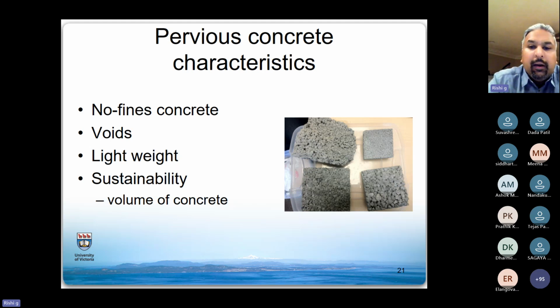Porous concrete or pervious concrete, of course, has lots of voids. If you look in literature, pervious concrete can have anything from maybe 5% of air voids all the way to 40%, 50% of air voids. The systems that you're looking at, the little briquettes that you see in the image, were roughly, give and take, in about the 25 to 30% air voids range.